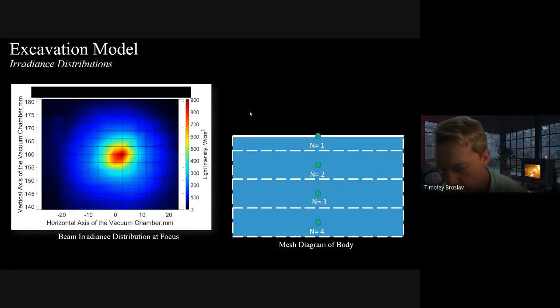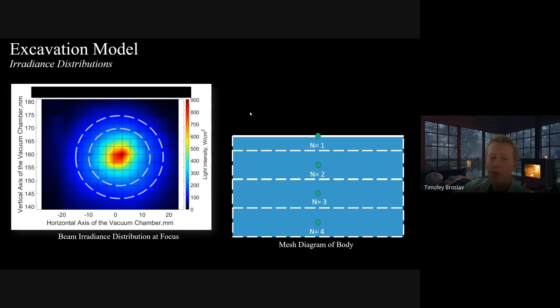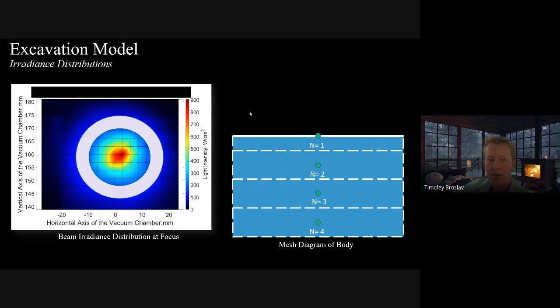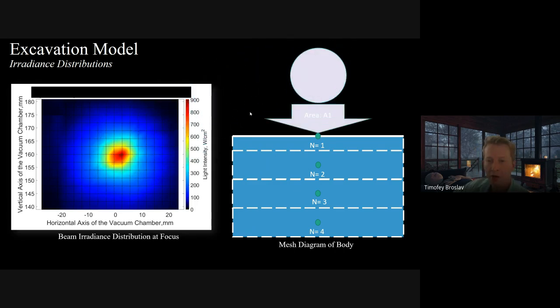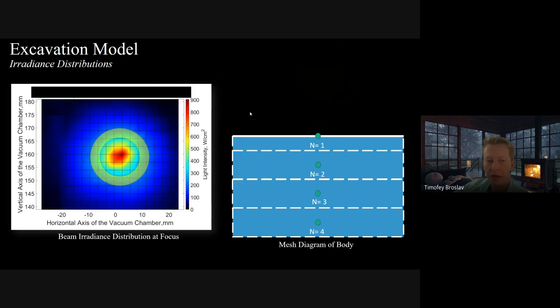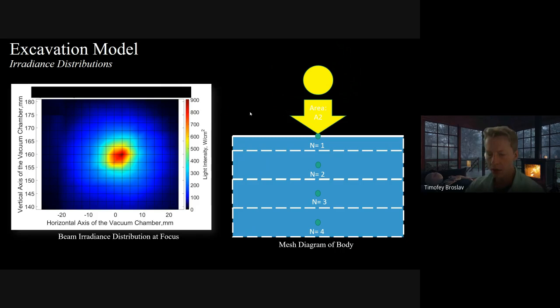Now, as I said, this model incorporated irradiance distributions because the beam of light that we were working with was not constant in irradiance. In order to incorporate this into the model, these heat equations that I just showed earlier were each solved incrementally for a certain area of the beam that fell under a certain irradiance range. So first we solved with the lower irradiance range. Let's say this is like 20 millimeters square or something. That would fall into the 200 watts per square centimeter. This is used as a boundary condition. Next, this is also solved for the more intense beam, and so on. And so this would have left a multi-dimensional array based on the irradiance level.